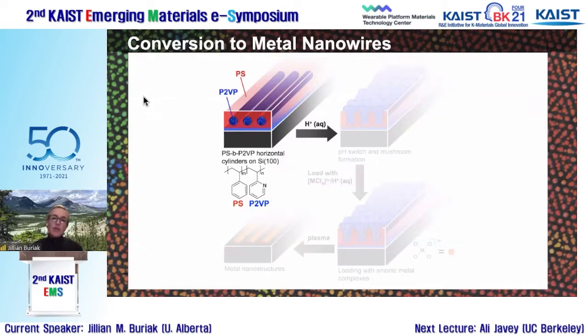But the chemistry that we came up to convert these block copolymers into more functional materials is this. And so in this case, if we made a monolayer just through self-assembly of a polystyrene poly-2-vinyl pyridine block copolymer, and you put that on a surface, you can see that the polyvinyl pyridine block is encapsulated in polystyrene. It's kind of like the wire of an electrical cord. So what's interesting and what's useful is encapsulated by polystyrene to kind of keep it inert and separated. So we go, okay, we would like to use the polyvinyl pyridine as the chemical handle through which we could functionalize the block copolymer, but it's encapsulated in polystyrene. But luckily, I had a mechanical engineering graduate student, Jinan Chai, who was working on this, and he had no fear of this. He's like, I'll get it to work.